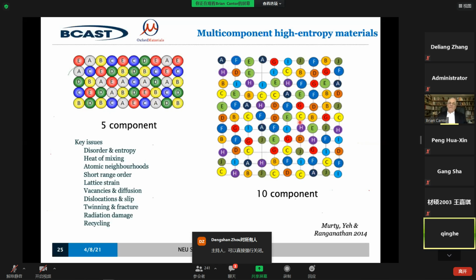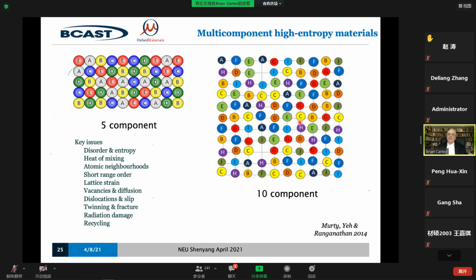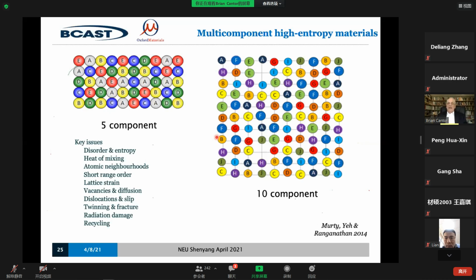Of course, there are different atoms at the different points in the lattice. We've got A atoms, we've got B atoms, we've got D atoms. A atoms, and in the 10 component, we've got J atoms, we've got H atoms. But it's more complicated than that, because the properties of an A atom depend upon its surrounding atoms, because it's affected by them. So this A atom is surrounded by, you can see, F, E, B, C, H, F, C, B. But this A atom is surrounded by a different set. Every A atom is surrounded by a different group. So the local structure varies from every single point, not just because we got 5 components or 10 components, but because of the surrounding atoms, the near neighbors of each initial atom.